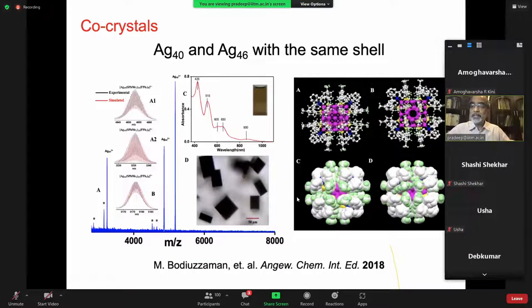When you do this, you find that you have a lot of variety. One thing we found was this cluster and this cluster both have similar external structure. The difference between this cluster and this cluster is six atoms. These six atoms, in fact, go into the cavity of this. As a result, the outer structure, or the ligand structure, is the same in all of these. As a result, they crystallize together, forming co-crystals. So in solution, you can see these two things coexisting, but you get only one crystal. That is because they co-crystallize.